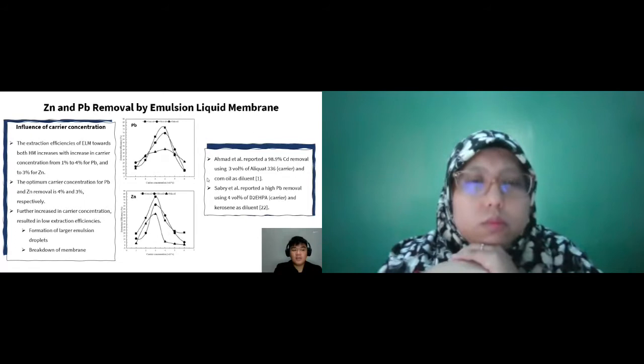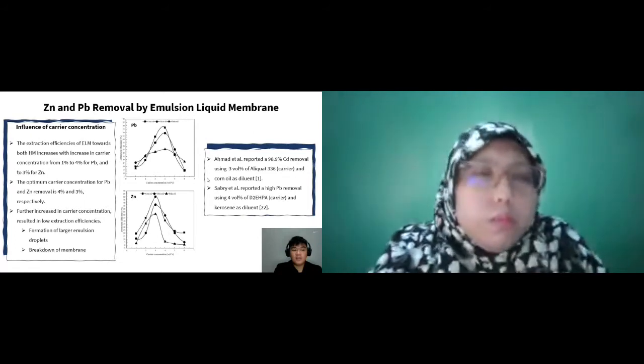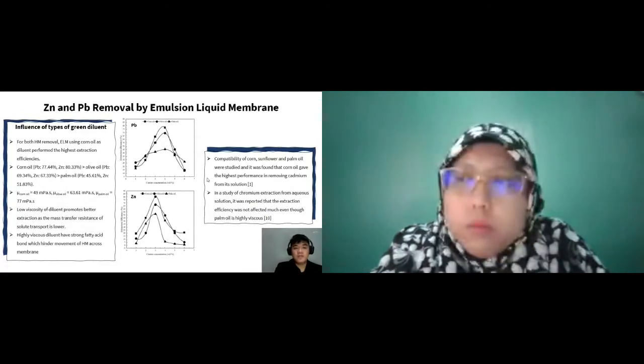Next is the influence of the types of green diluent used in the emulsion liquid membrane. The graph shows that for both Pb and zinc removal using emulsion liquid membrane, corn oil performed the highest extraction. Corn oil removed Pb and zinc the best, followed by olive oil and palm oil. It was found that the viscosity of the vegetable oil affects the extraction efficiencies. Based on the viscosity analysis, corn oil has the lowest viscosity among the green diluents used. Corn oil has a viscosity of 49 millipascal second, while palm oil has a viscosity of 77 millipascal second.